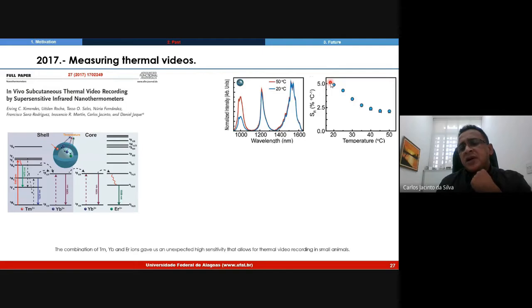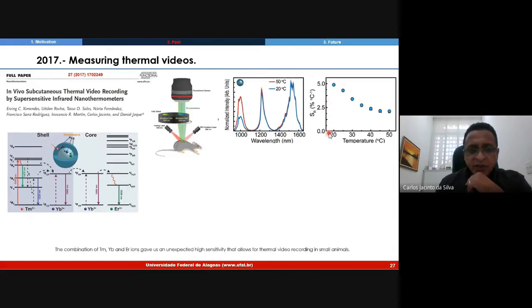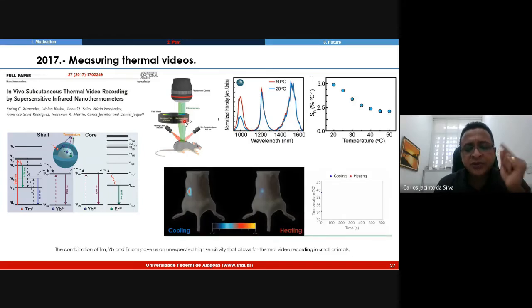room temperature nanothermometer with a relative thermosensitivity of 5% degrees Celsius minus 1 at 20 degrees Celsius. Using one well with a band pass filter, allowing to pass this band at 1,000 nanometers, and another at 1.2 micrometers, it's possible to detect one emission with a time delay of more or less 3 seconds and perform the ratio of them. The subcutaneous thermovideo of the temperature is obtained, and it's possible to do it over time.